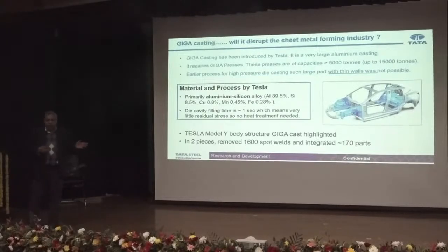Aluminum is expensive, everything. Still the cost of ownership for the auto manufacturer is about 8 to 10% less. One reason is, if we want to make this and this using the typical stamping route, we need to make at least 70 parts. To make one part, we need 3.5 operations on average. So we need almost 220, 230 dies, 230, 240 operations, so many inventories, etc., and then do the welding of 70 parts. So there is huge complexity in the whole supply chain. That complexity is replaced with what? One component, probably 3 operations, right? And that helps reduce the overall cost of ownership, even though aluminum is more expensive.